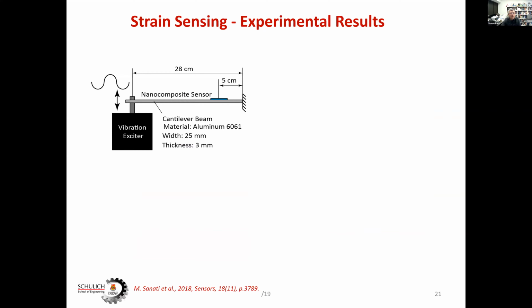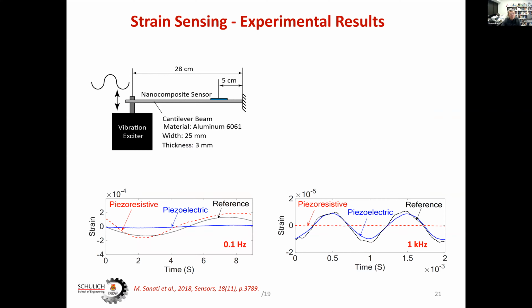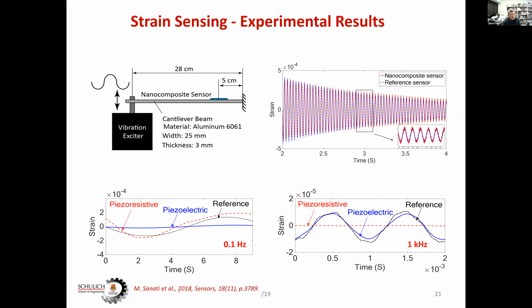And we did some shaker testing. So this one here is exhibiting very low frequency. Right now we are moving very slowly. So this is a range of earthquakes and so on. And it's not very easy to make sensors that can measure very small displacement or frequency. As I said before, by using piezoresistive characteristics, we can measure pretty okay, whereas the piezoelectric doesn't quite measure.